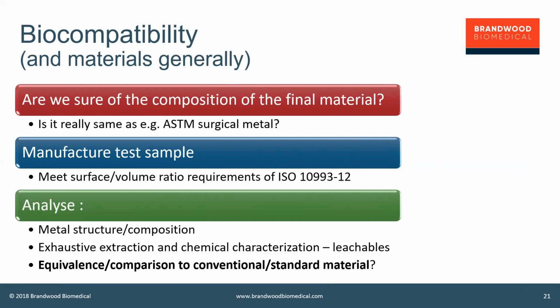Do metallurgy if necessary to look at the final structure of the metal, and do exhaustive extractions and chemical characterizations. An exhaustive extraction is when you take the sample and you place it into a solvent for a defined time period, usually at an elevated temperature. Typically for implants, you'll be looking at 70 degrees for 24 or 70, 48 or 72 hours, but an accelerated temperature for a reasonable length of time.